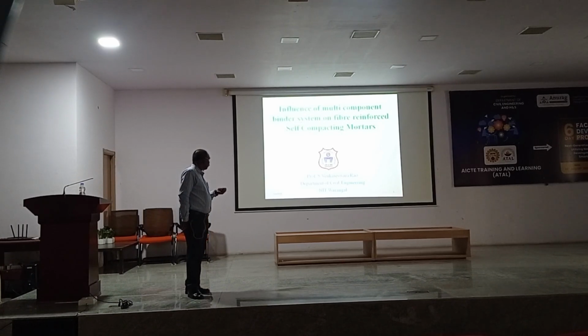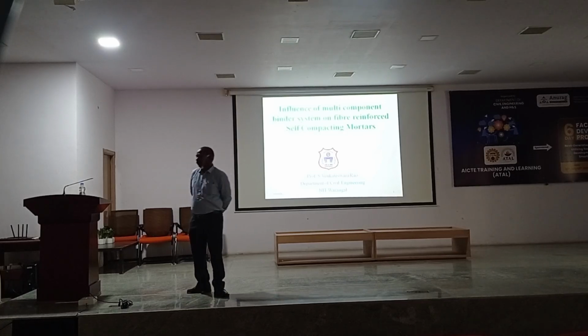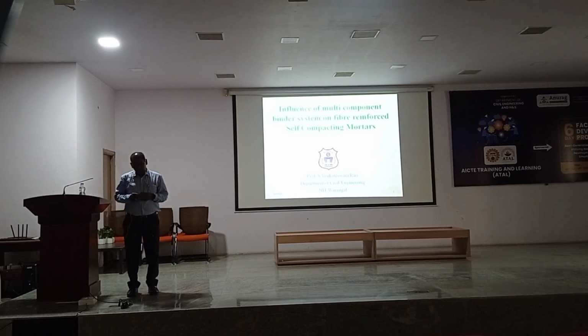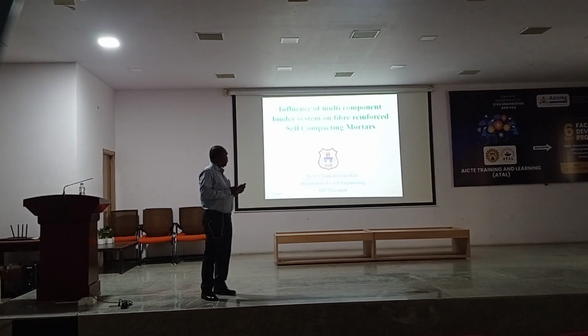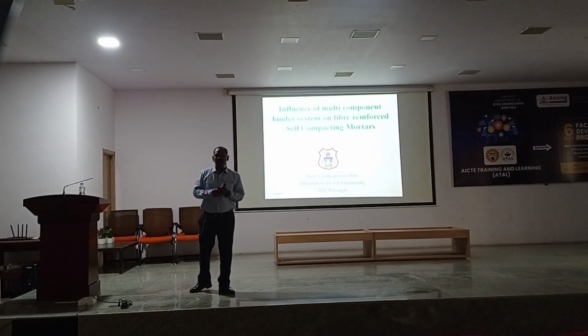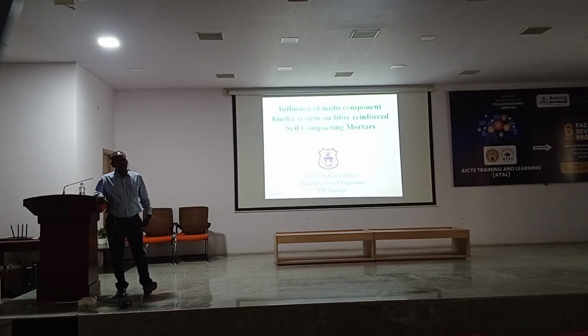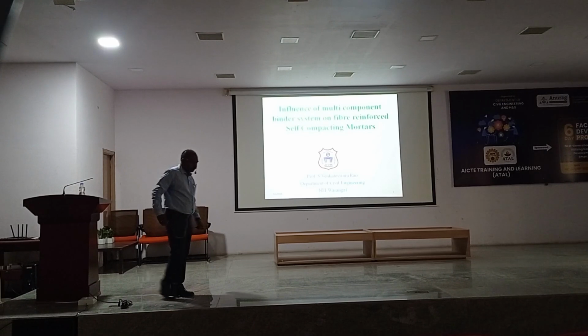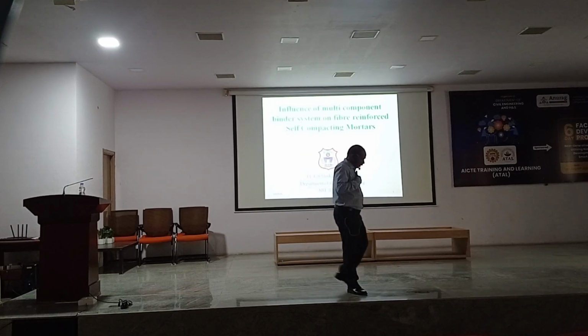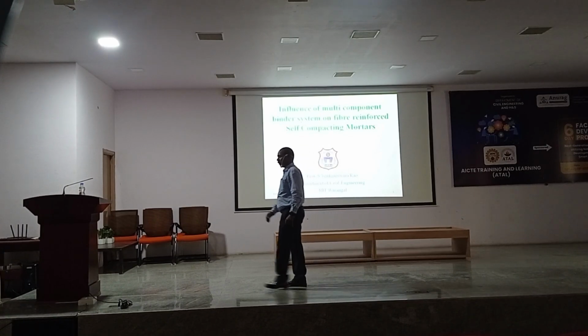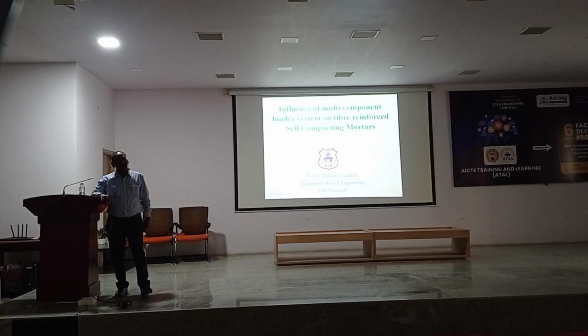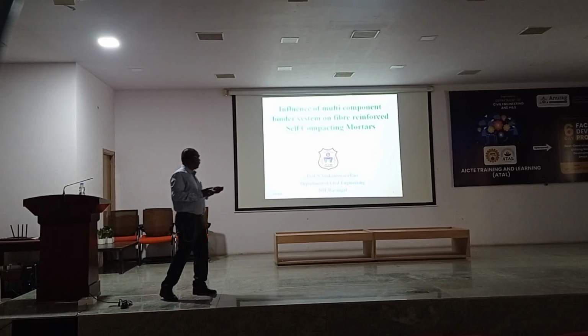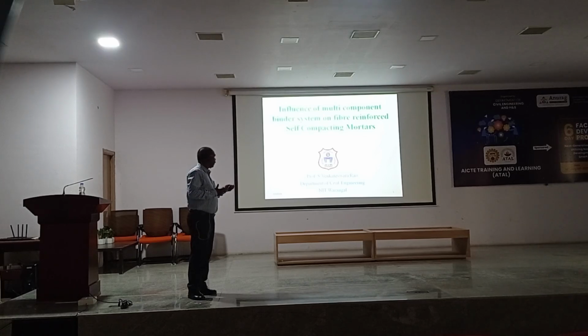What is the application of this fiber reinforced self-compacting mortars? Earlier, we used fiber reinforced self-compacting mortar with nanomaterials, and the application is repair material. But here, you can use this fiber reinforced self-compacting mortar as a repair material and also as shotcrete. Anyone know shotcrete? For stability of the walls in the tunnels, and for stability of the walls in the mines, shotcrete. If anyone has recently gone to Tirumala, you can observe that shotcreting, because I observed that. Shotcreting in the ghat road is there. They put some anchoring and pneumatically apply it. Shotcreting is nothing but pneumatically applying that material with high pressure. There are two types of shotcrete actually, dry mix and wet mix, that is a different story. And in that mix we are using this fiber reinforced self-compacting mortar.